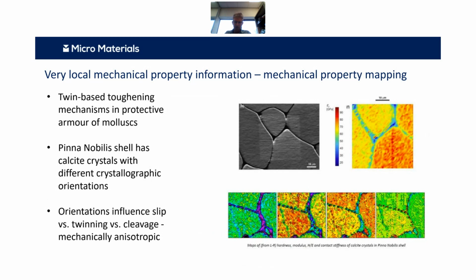So there's some examples here where the instrument has been used, in this case by a group in, I think, AGH in Poland, to show how this seashell essentially has calcite crystals with different crystallographic orientations, and these orientations influence the relative proportions of slip and twinning and cleavage that occur. And so you can pull out differences in this and understand how that builds into the toughening mechanisms that these protective armor, these mollusks, have. And once you have this information, then maybe you can use that knowledge to design better materials.